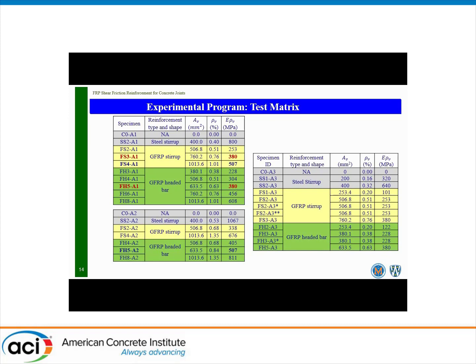We used 2, 3, and 4 GFRP stirrups. Then H refers to headed bars. We tested another specimen with the same 30 MPa interface using 3, 4, 5, 6, and 8 GFRP headed bars. Series A2 is where we reduced the length of the interface.